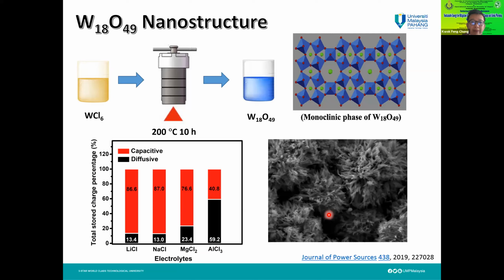So we find something very interesting. It means that we've proven that with our material, the aluminum ion can go in and diffuse very freely in the crystal structure of this tungsten oxide.